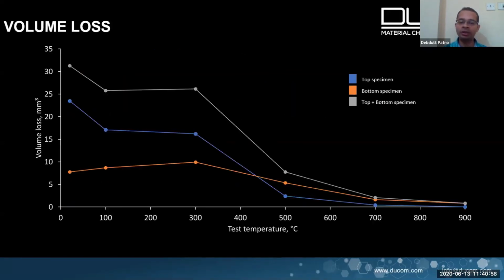We also measured the wear, or how much material was removed from these surfaces as a function of temperature. Y-axis again shows how much wear has happened in volume loss, millimeter cube, as a function of temperature. Again, the same trend. If you start at ambient, which is on the extreme left, is very high wear, and when you go to higher temperatures, exceeding 700, you get very low wear. So surprisingly, when you take some of these advanced materials and rub against each other, as temperature increases, the friction and wear drop down dramatically.